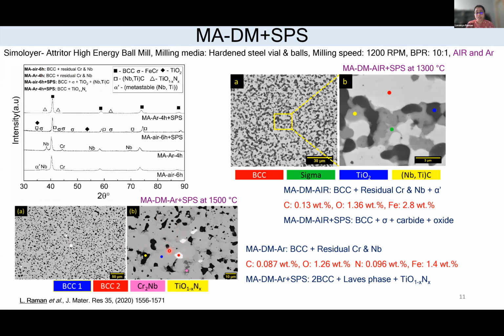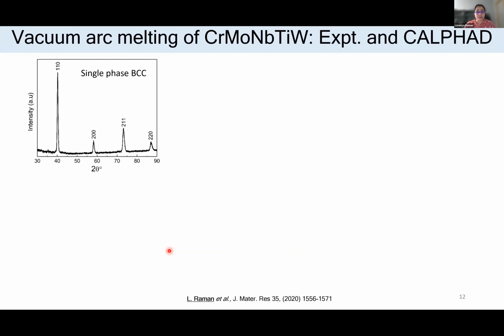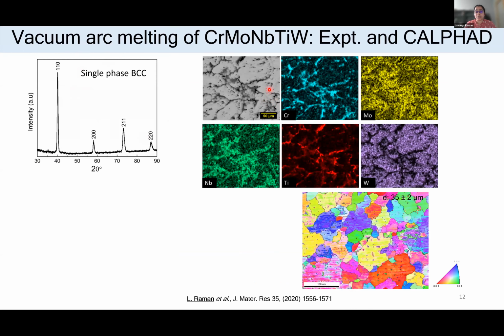Summing up this last slide, when we make these alloys through the powder metallurgy route, they are very sensitive to the milling conditions, atmosphere, and milling media. They decide what secondary phase you can expect. When we made the same composition using arc melting, we obtained a single phase BCC. This is the SEM microstructure, wherein we can see that elements segregate into the dendritic and interdendritic regions according to their melting point.